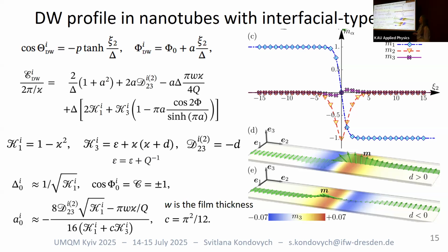The preferable sign of the phase slope is actually positive, and depending on the sign of DMI, magnetostatics can either compete or work together on the value of the phase slope. So this is just an interesting deformation of the domain profile. However, chiral effects are not expected.